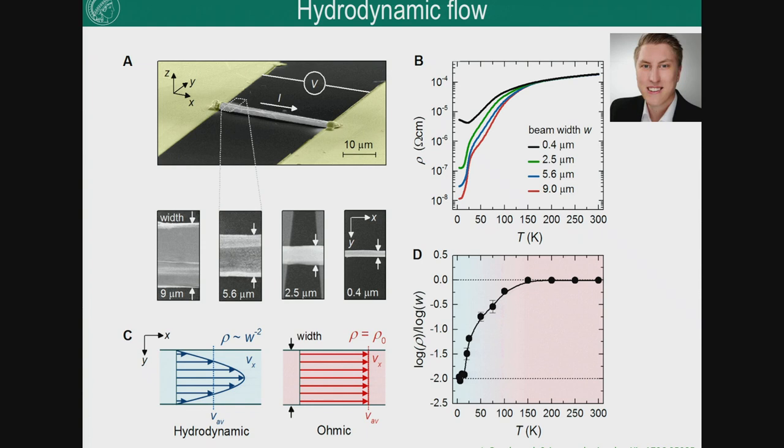So we made crystals of different size. And we really see that the resistance changes strongly, so it goes up and it can become even very resistant. And this is not only tungsten phosphide. If you look at the experiments in the literature, it's there for cadmium arsenide, for the Dirac semi-metals, and for others also, even if people did not investigate it under this aspect.